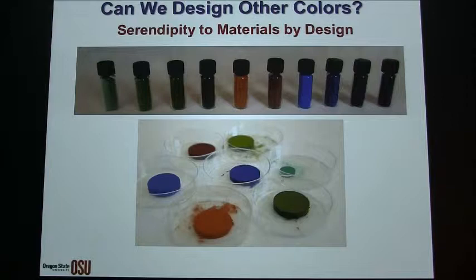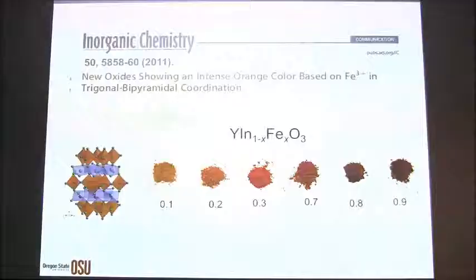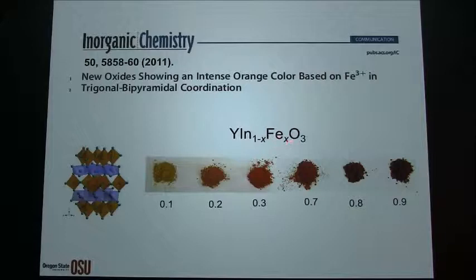We are still working on it, but we still don't have a handle on exactly how we are going to make it work. We know we can make orange, but bright red is hotter actually. But the orange pigments, what we did was, instead of manganese, now we simply use iron. In the same crystal structure containing indium, instead of completely removing the manganese, we put in some small amount of iron, and it sits in the same crystal structure. So instead of giving you a blue, now we get an orange to bright, kind of a brown, but it is more like a dark brick red color actually. So we can create other colors.